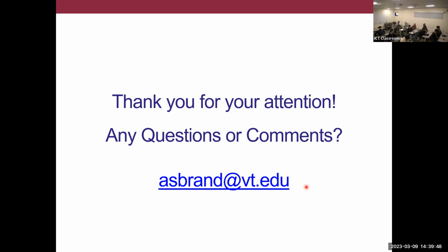Great presentation, Alex. Going back to the basics of some of the admixture stabilization reactions, like lime reactions or cement, the same calcium-based stabilizers, there is always, especially with the organics, this cation exchange capacity of organics so high, it prevents any kind of chemical reaction, therefore, with the cement reaction or calcium +2 reaction. Is that a way to maybe look at this, is organic blocking things?